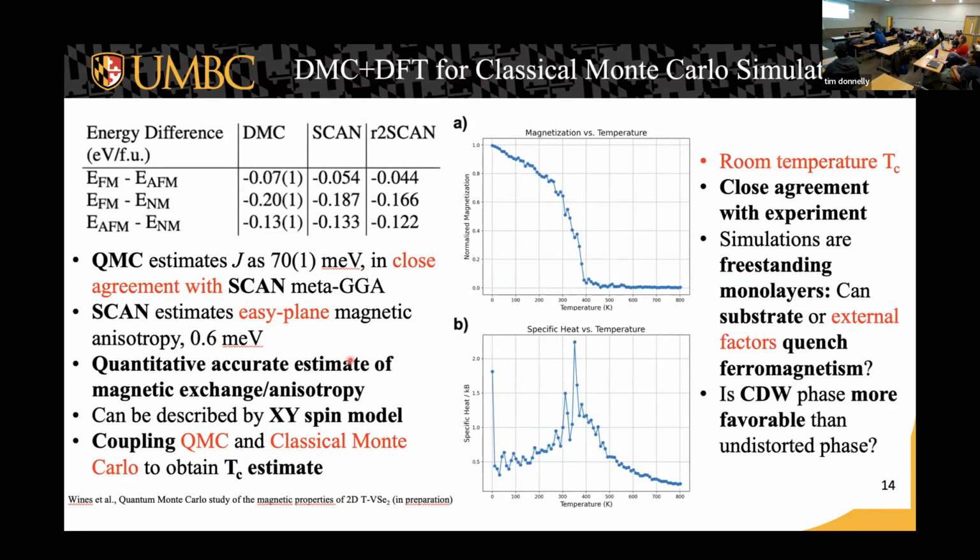Afterwards, what we have done, we have written our own developed magnetic Monte Carlo code here, and we try to estimate the Curie temperature in our Monte Carlo code. And what we have seen right now, it only contains one parameter, the Heisenberg exchange. We are right now trying to improve it by DMI interactions and by including other anisotropic terms as well. But we see some kind of a nice shift from non-magnetic to magnetic case around 400 Kelvin. So this is also observed in the experiment.